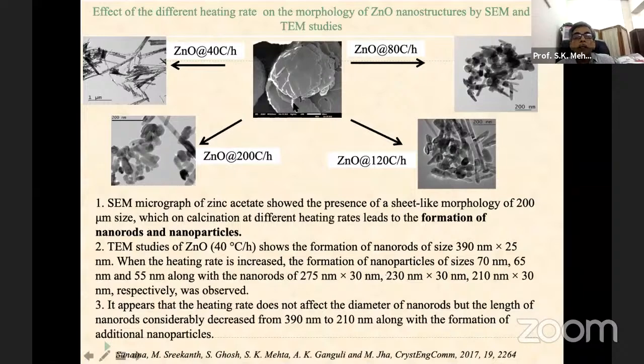So this is our zinc oxide, and if I heat it at 40 degree per hour, you can get this. If I do 80 degree per hour, I can get this here. If I do 120 degree, I get this here. And 200 degree, you get this here. So these are some micrographs. You can see the presence of sheet-like morphology of 200 micrometer size, which on calcination leads to the formation of nanorods and nanoparticles. So the zinc oxide at 40 degrees centigrade shows the formation of nanorods.